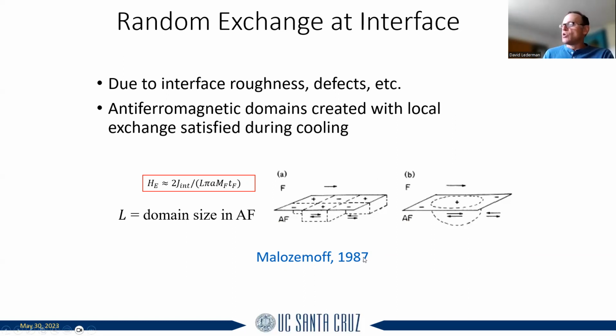Okay. And so this model predicted an exchange bias that's a slightly different formula. It looks similar, except that now it scales inversely with the domain size in the antiferromagnet. These are domains that are formed in the antiferromagnet, and so this would decrease the effect to something reasonable, something that agrees with experiment.